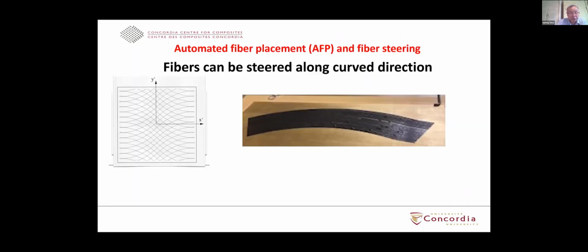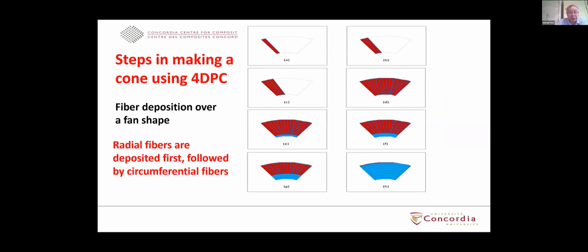If you do that by hand layup, you cannot make this kind of structure. So you have to use an automated fiber placement machine, which has the capacity to steer the fiber. In this case, you can steer the fiber along a curvilinear direction, and you can also lay the fiber along the radial direction. In terms of the step-by-step procedure, at the beginning, you lay down the radial fiber. You make the first strip of the fiber, then another strip, 2 strips, 3 strips, and you continue until finally you have the whole surface of the trapezoid.